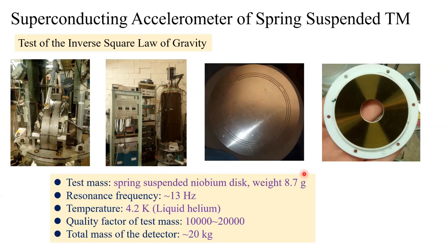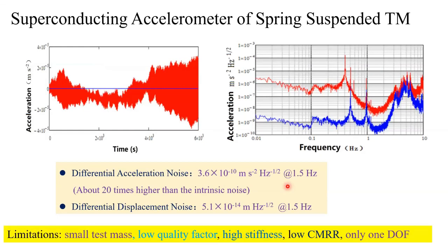a detector. This detector was originally designed to test the inverse square law of gravity, since Yukawa and other theorists said gravity does not follow an inverse square law. So we wanted to test it. In this detector, we use a mechanical spring suspended niobium plate as our test mass. This test mass is very small, its weight is less than 9 grams. The resonant frequency is 13 hertz, and it's very stiff. The temperature is liquid helium temperature. The quality factor is not too high, about 10 to 20 thousand. So with these four parameters, our result is not that bad.